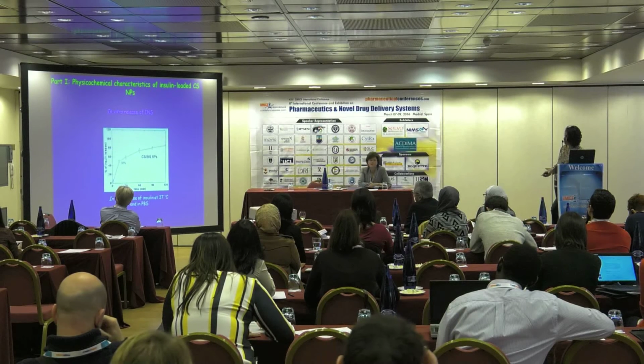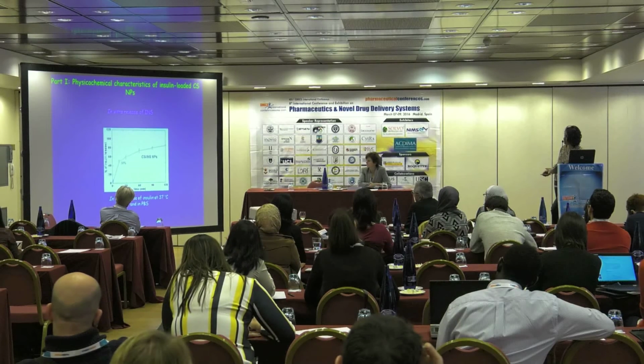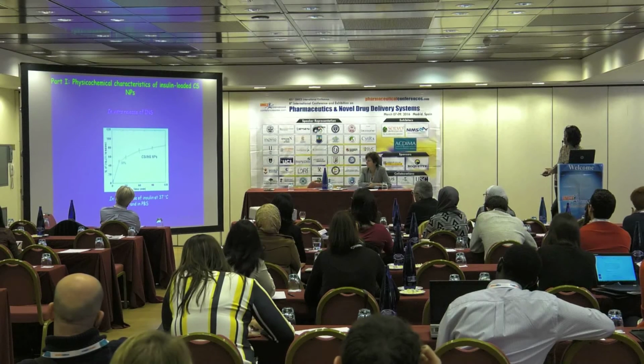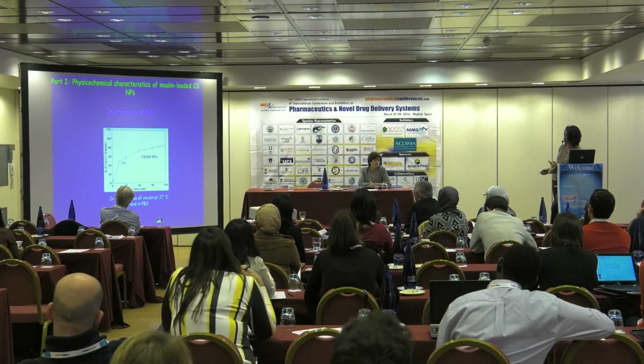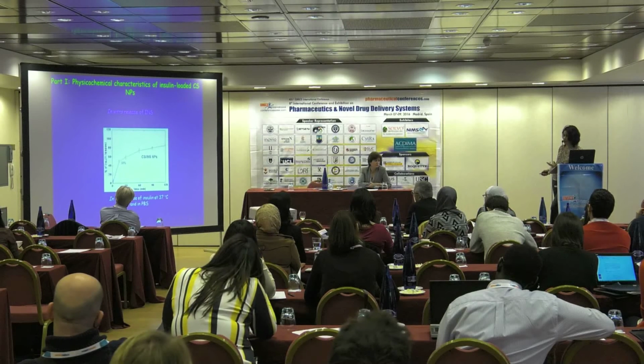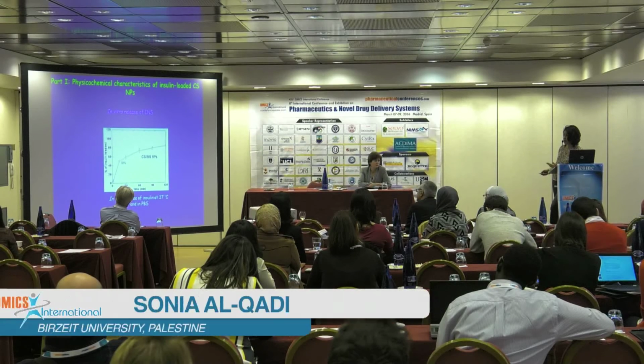So we have 50% of the protein released in this kind of burst release, and this indicates that we start to assume that we might have a proportion of insulin dissolved at the surface of the nanoparticles, and another proportion encapsulated in the core. This also indicates weak binding, actually.